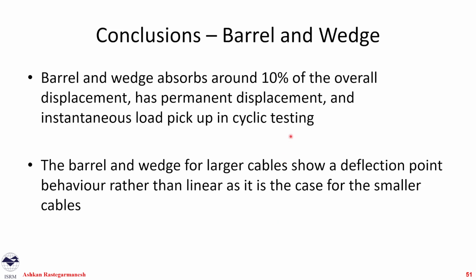For our barrel and wedge, we realized that less than 10% of the movement is stored in barrel and wedge, but those movements are permanent, and we have instantaneous load pickup when we do loading and unloading. And we realized that the larger cable barrel and wedge have a slightly different behavior, but probably this doesn't make that much difference in the bigger picture of the topic that we're talking about.